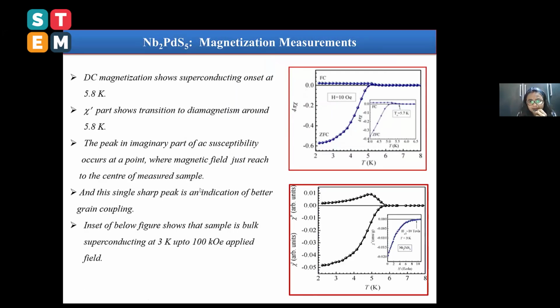And this is the DC magnetization measurement, which shows the onset superconducting transition temperature at 5.8 Kelvin, while the real part of AC susceptibility also shows the transition at 5.8 Kelvin. The peak in the imaginary part of AC susceptibility occurs at a point where the magnetic field just reaches the center of the sample. This single sharp peak is an indicator of better grain coupling in the Nb2PdS5 sample.